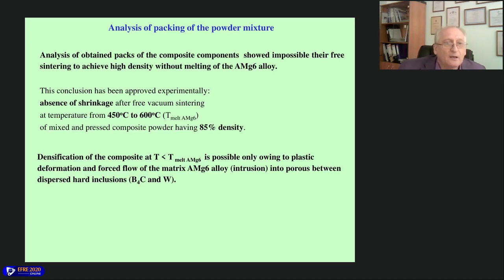So analysis of the obtained packs of the composite components showed the impossibility of sintering these components to achieve high density without melting of the aluminum magnesium alloy after pressing. And this conclusion has been proved experimentally: absence of shrinkage after vacuum sintering at temperatures from 450 degrees C up to 600 degrees C. No shrinkage of the mixed and pressed composite powder, and in this case, we obtained just 85% density.